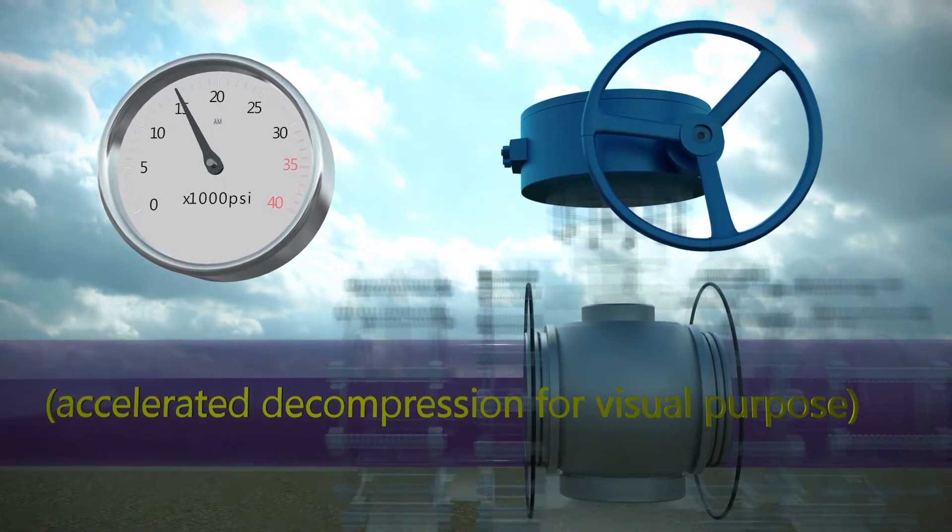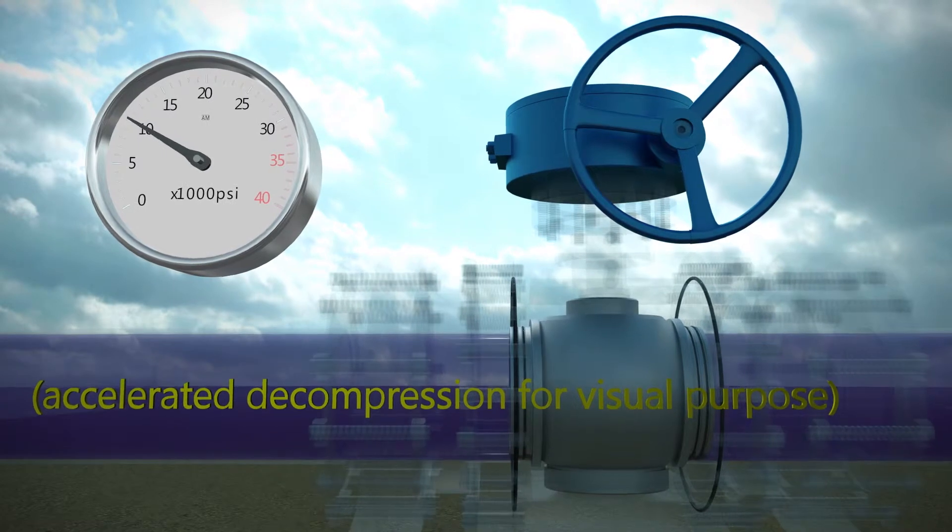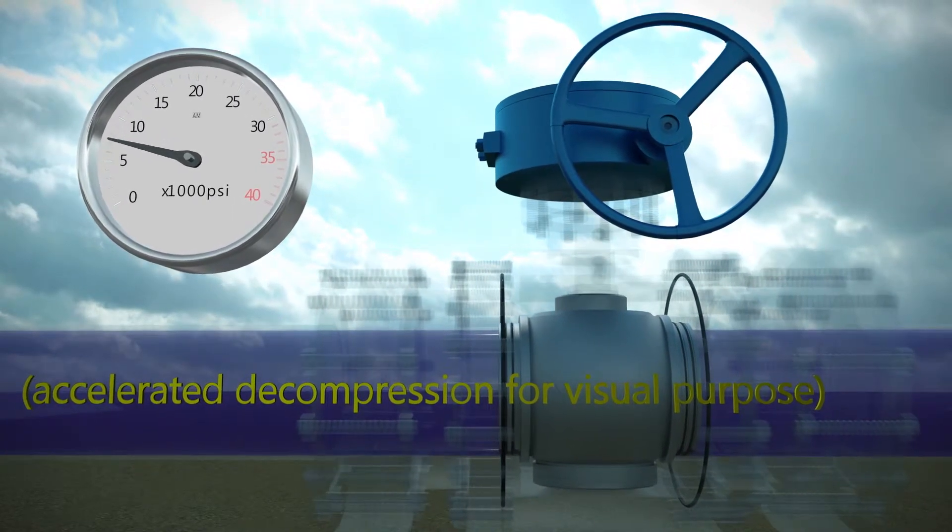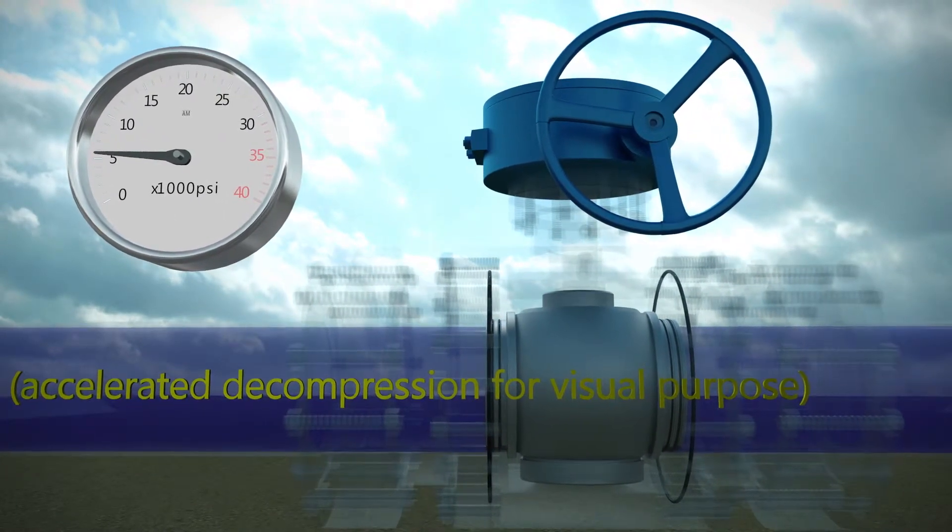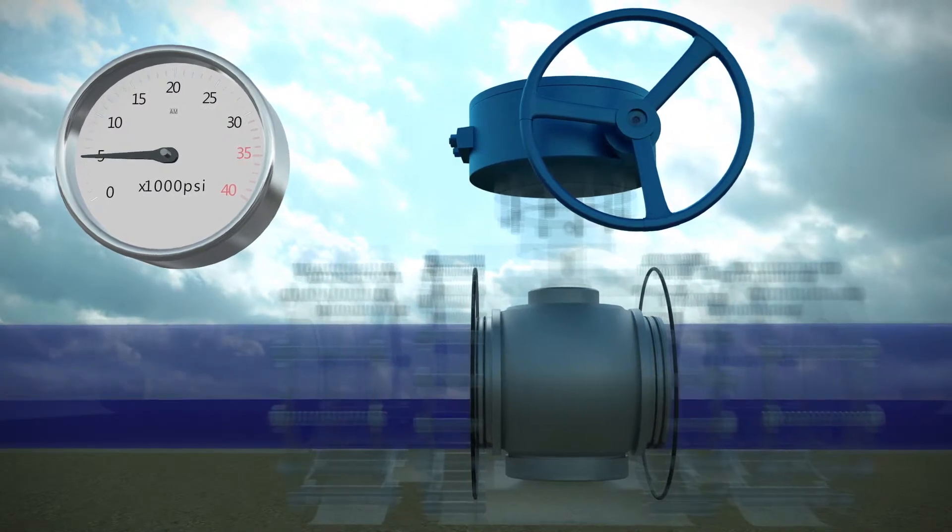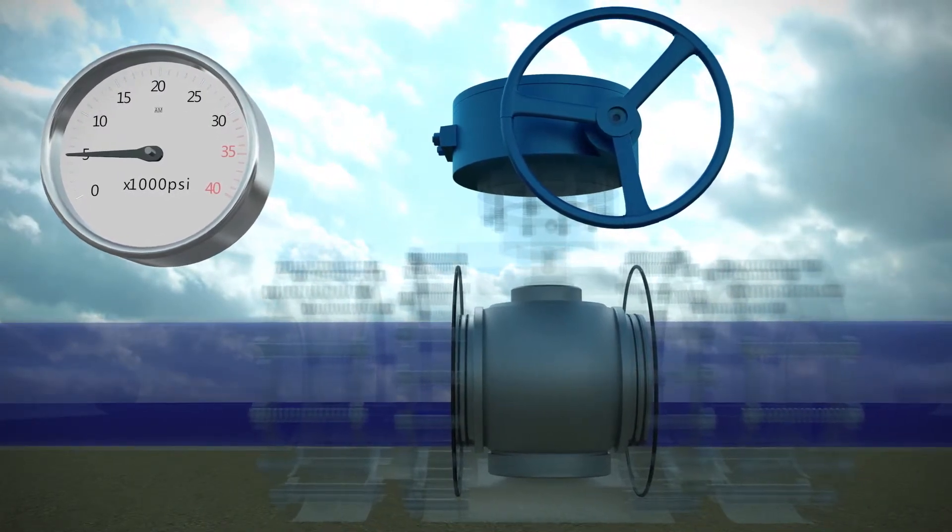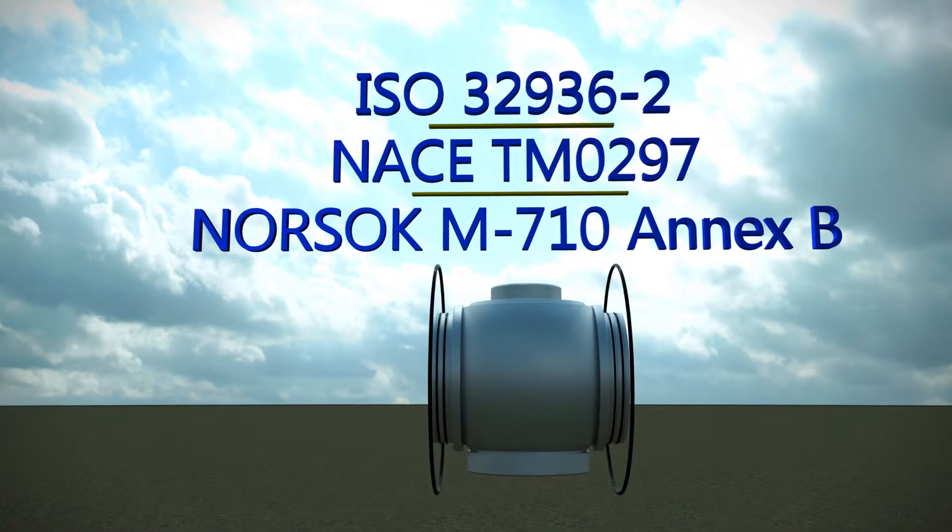However, if the rate of decompression and expansion is high, the trapped gas within the seal expands beyond the material's ability to contain the gas bubbles, causing fissuring and resulting in seal failure. Endura materials are tested and certified to various ED standards.